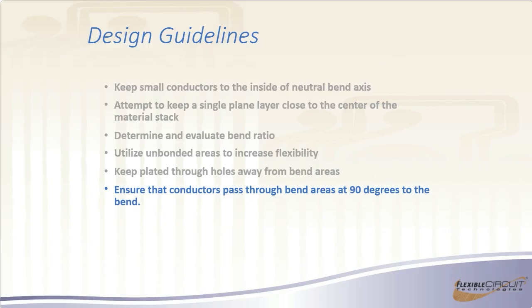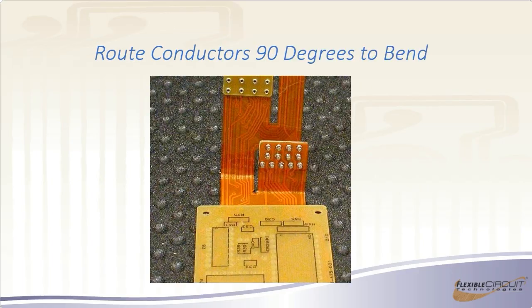You want to make sure, whenever possible, your conductors pass through your bend areas at 90 degrees. And by that, I mean, if you look over on the left side, you can see that all the traces are going through perpendicular, but over here, they're going through at an angle. And this isn't a problem by itself if it's a static application. If it was going to be high vibration or semi-dynamic, it might be more of an issue. But if you can go through perpendicular to the bend, that's the way you want to go.